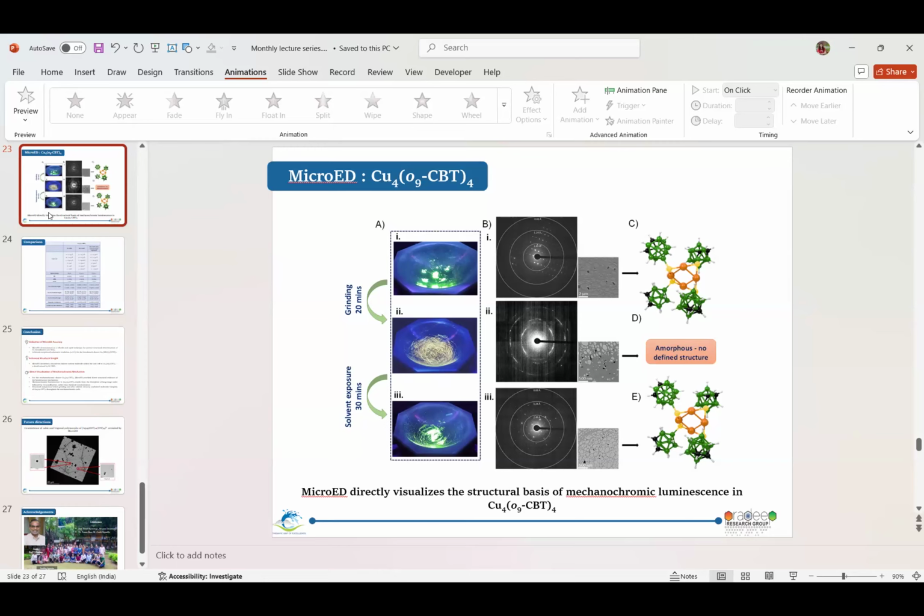Yeah, exactly. I think we are mingling two terms here. One is crystallinity and one is long range order and disorder. Both are different. Harshita, I think somewhere you said it is increasing the crystallinity. Actually, it's not increasing or decreasing the crystallinity. It's actually the long range order that is going and coming back. If you give the explanation in that manner, then all these confusions will evaporate.